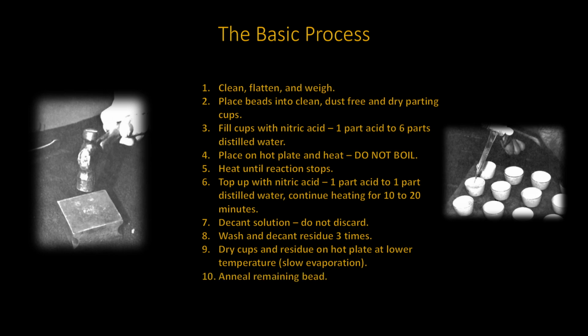After which, anneal the beads, which will be explained in this presentation. Once annealed, weigh the beads. The difference in weight will be the amount of silver that was contained in the doré bead. This can be used for the inquartation process if required.